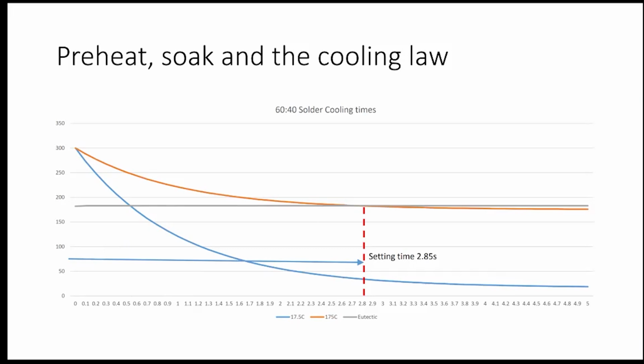I make that about 2.8, 2.9 seconds. Now that taking 3 seconds to set means that the solder is annealing very, very gently and I'm not going to get dry joints. Quick cooling is what causes dry joints, and dry joints are the most common problem that we debug in soldering. If you go to the Neil's soldering sessions, you will see dry joints. They happen, particularly if you've got a wee bit of board and it's moving, or you're trying to move it around about the bench, or you're breathing on it.